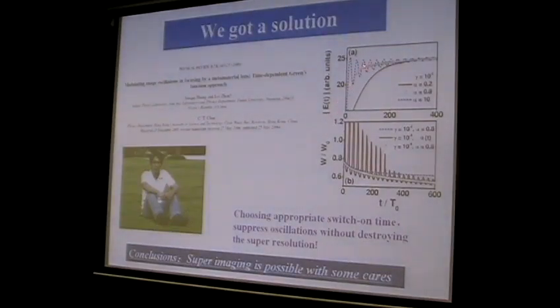So this is the calculation result. Indeed, we can have an optimal switch on time in which we have a very good solution and we can suppress the oscillation. So the conclusion is that super imaging is still possible. However, we have to implement it with some care.